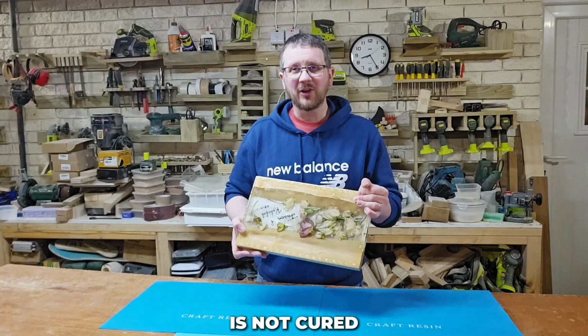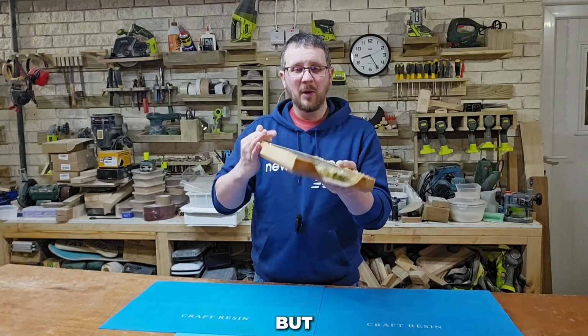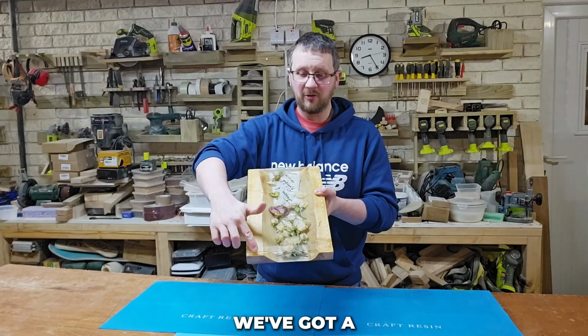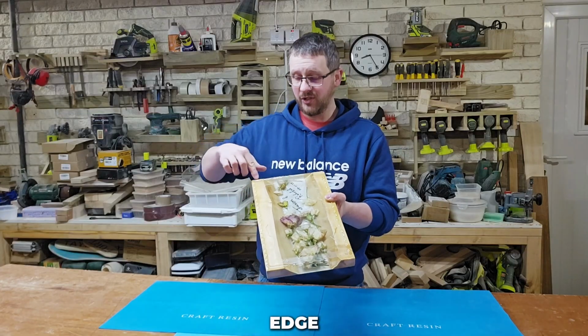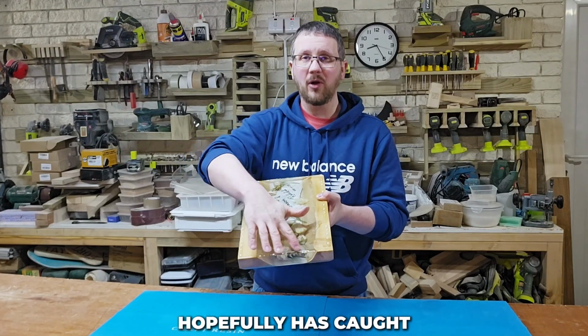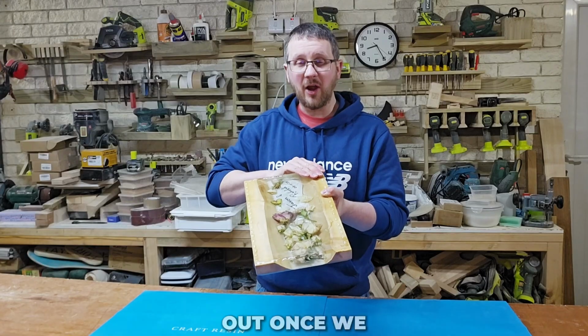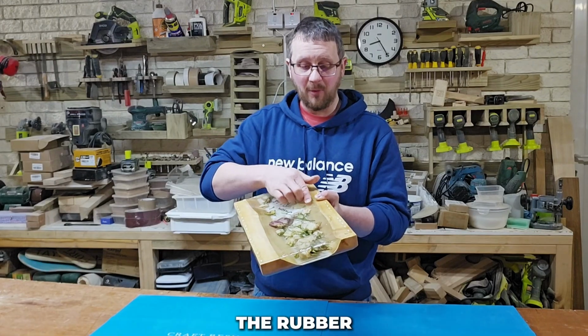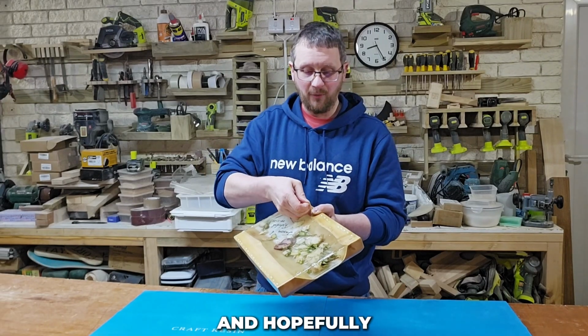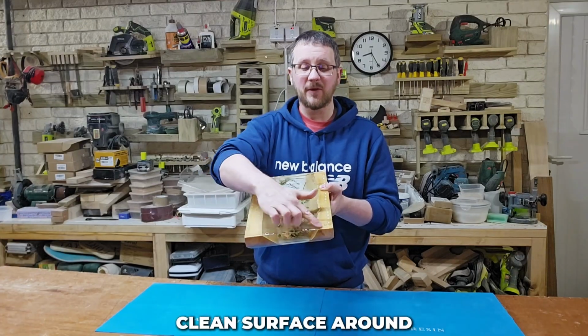The coat is not cured, but as you can see, we've got a row of drips all around the edge. Now, our silicone hopefully has caught all those drips, but we'll find out once we start peeling off the rubber silicone, and hopefully it'll leave a nice clean surface around the edge.